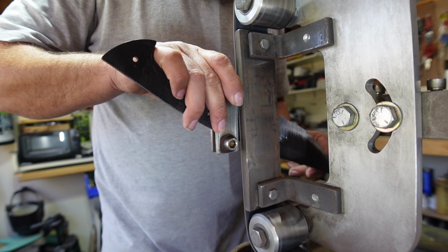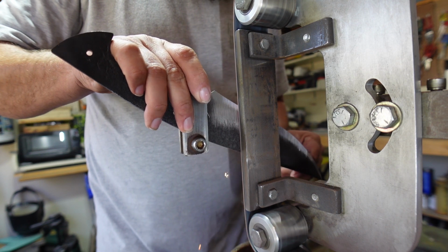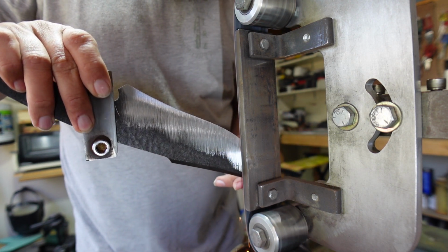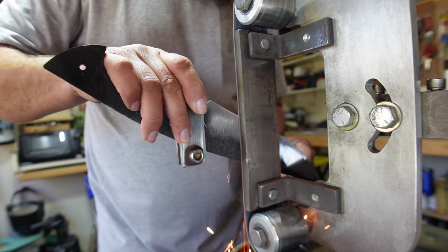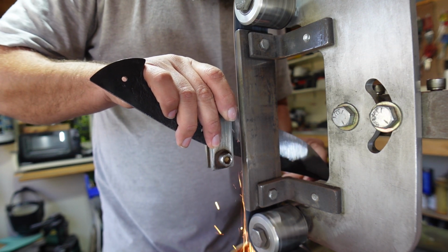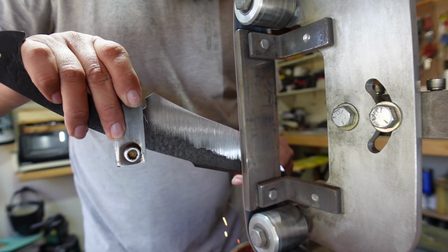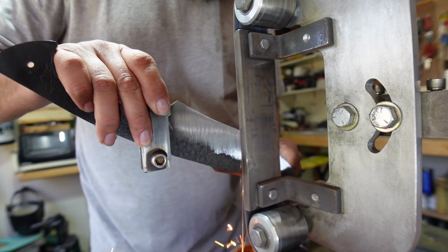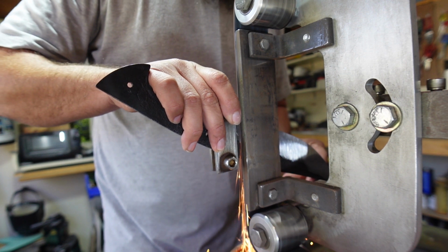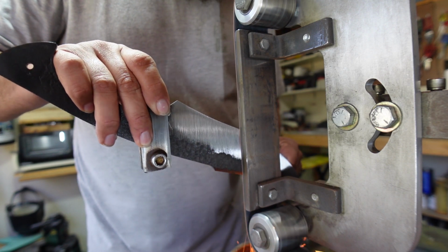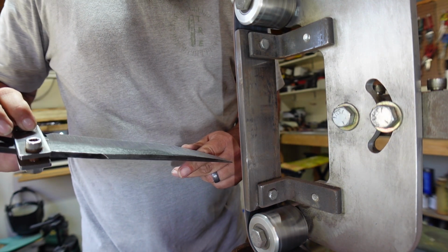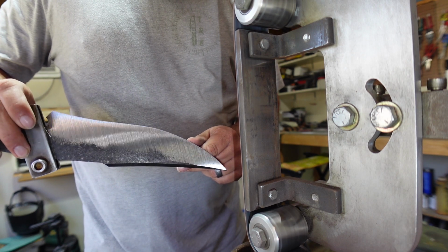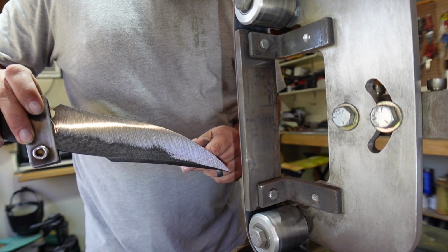Once we did that, we file tested it, and then I took it inside my house and tempered it inside my home oven because it wouldn't fit in my smaller oven that is inside the shop. So once we tempered it, which was at 375 degrees for 2 hours, we were able to start grinding it. And this first grind is just grinding off the decarb layer, getting all of that gone so that we can then start evening out our bevels and getting them exactly where we want them.